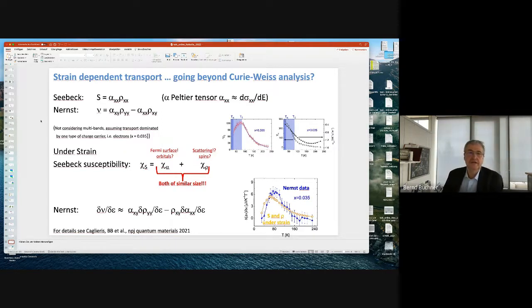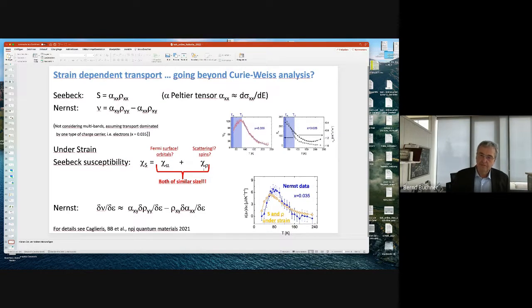You can do an analysis, and you can discuss it in more detail if you want. So you can write that the Seebeck effect is connected to, let's say, the Peltier tensor and the resistivity tensor, in the same way the Nernst effect. And then you can separate these strain dependencies into Fermi surface changes, which come from this alpha, and more resistive changes, scattering. And they are of similar size. So both things happen here. People say that probably this chi_rho could be related to scattering, to spin degrees of freedom, but here most likely orbitals play a role.